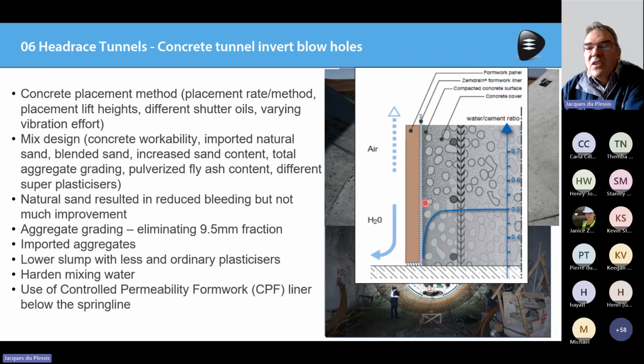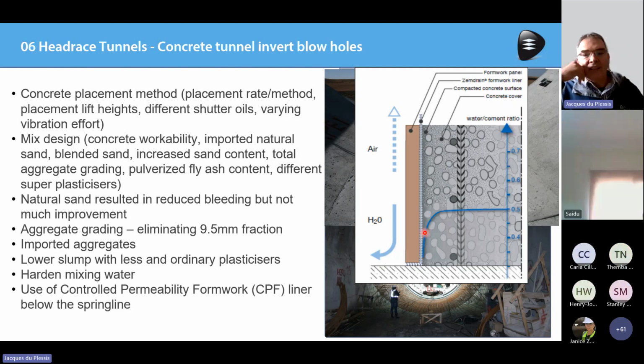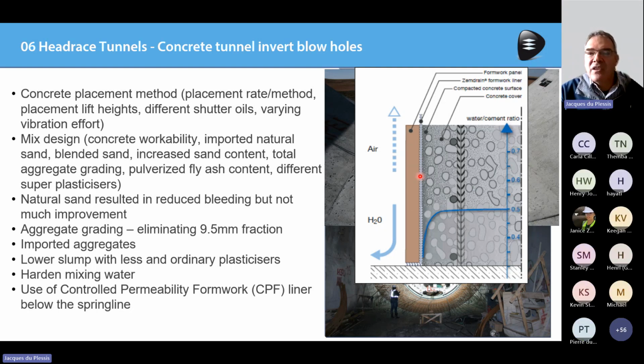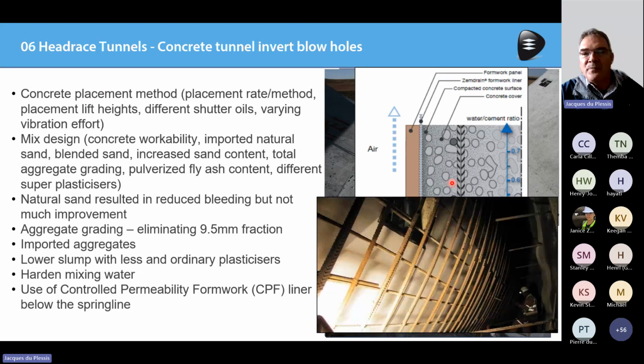And the result of that is you also reduce the water cement ratio against the shutter. In the first 1 or 2 centimeters against the shutter, you draw your water cement ratio right down to as low as 0.4. So you end up with a very strong, very durable concrete against the shutter and against the flow. So it makes a lot of sense for tunnels. Our flow velocities in these concrete tunnels went up to as high as 5 meters per second. So you can understand why this CPF liner was specified. So I think a very important lesson we've learned there.